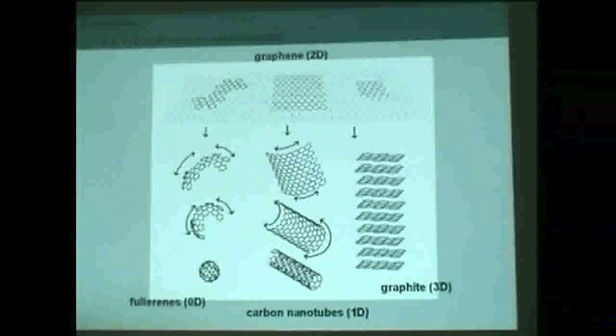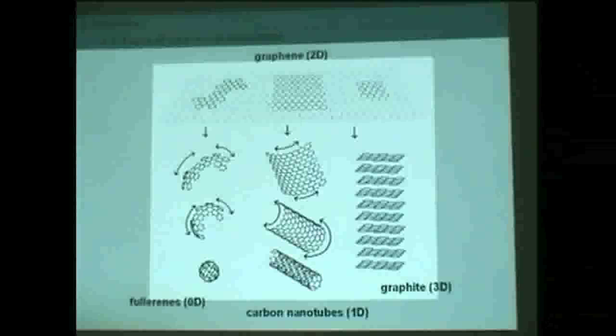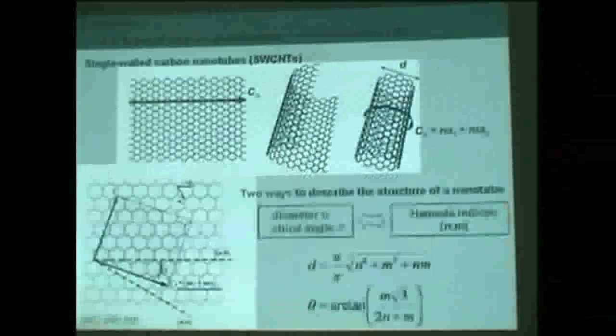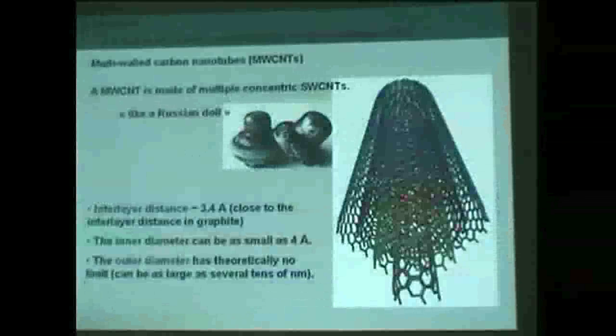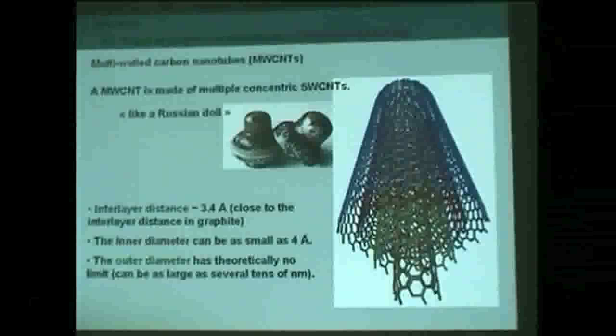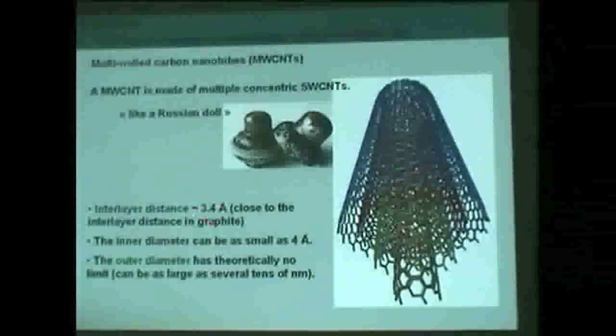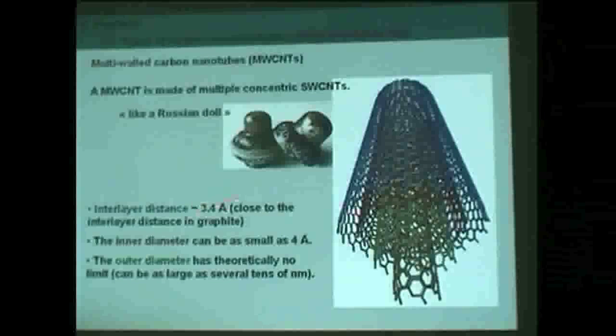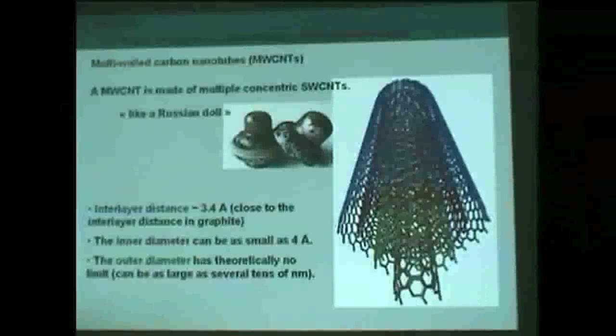This is the case of natural graphite. It's also the case in multi-wall nanotubes, because multi-wall nanotubes are in some way just bent graphite with many layers of graphene. This is bent graphite. As a consequence, the van der Waals distance is close to graphite, about 3.4 angstroms.